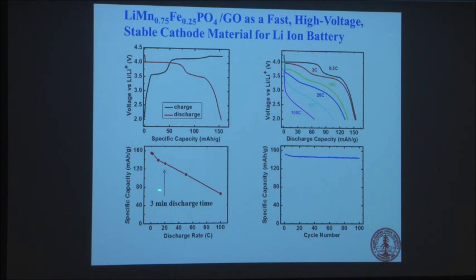For example, in this 20 C case, which takes 3 minutes to discharge, the capacity is still above 100 milliamp hour per gram. It's a very fast discharge process, and the stability is pretty good.